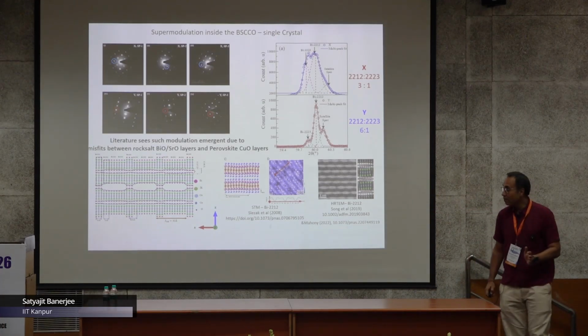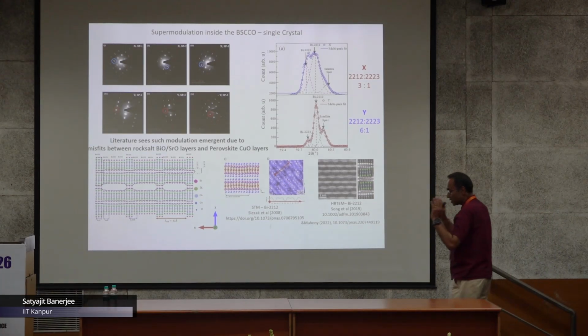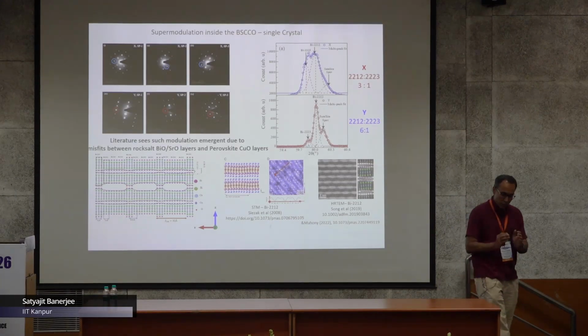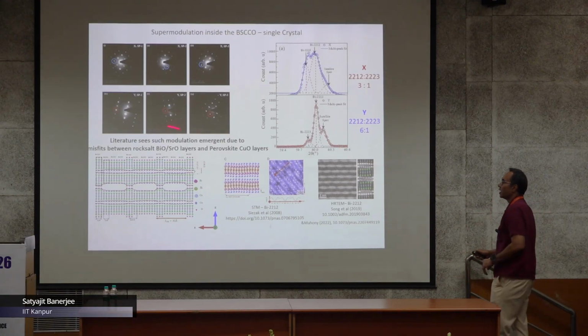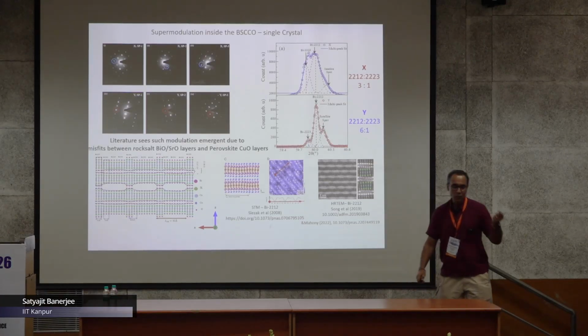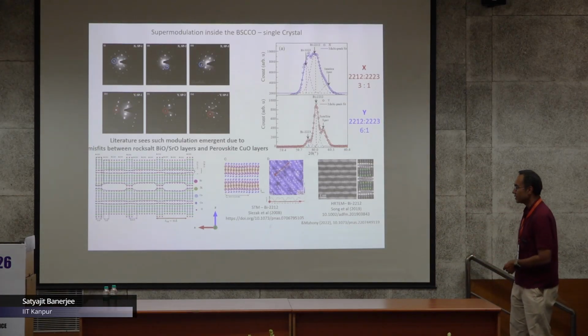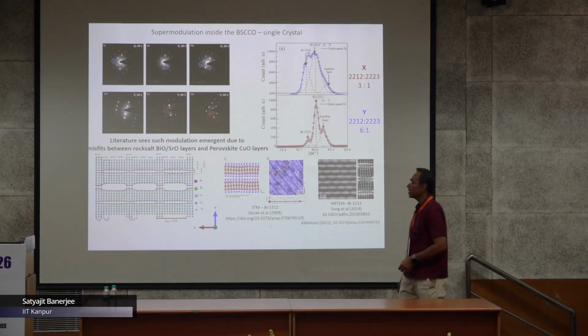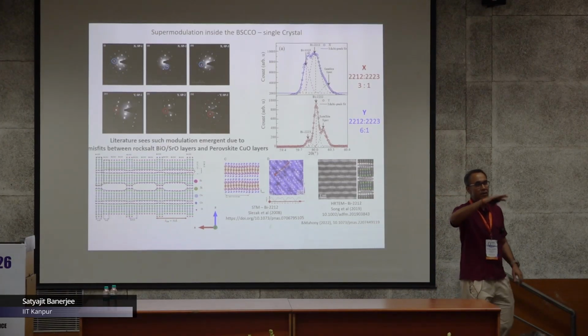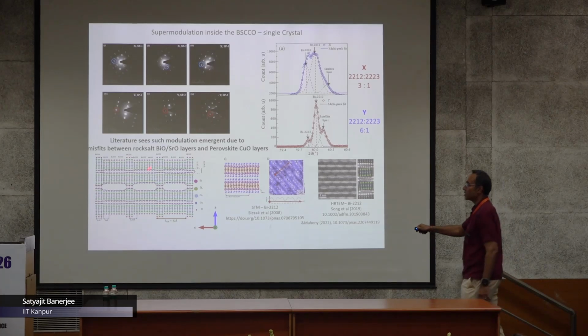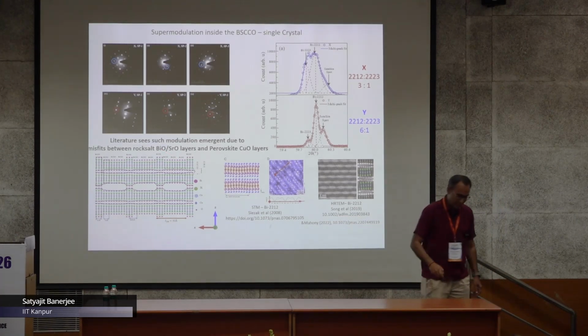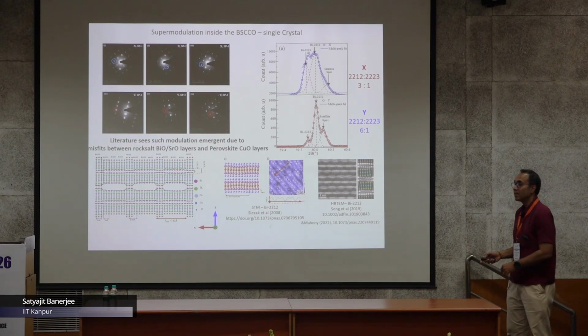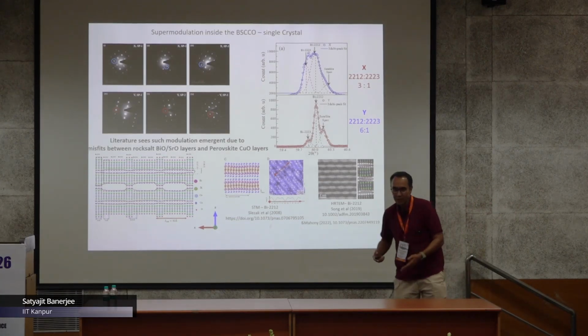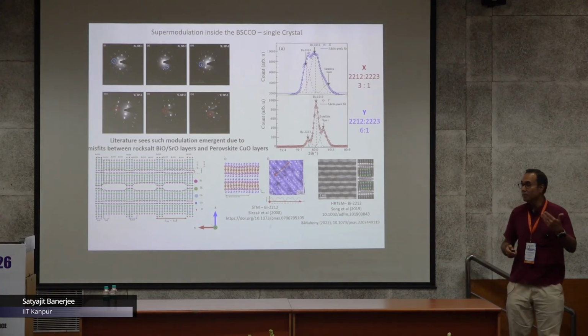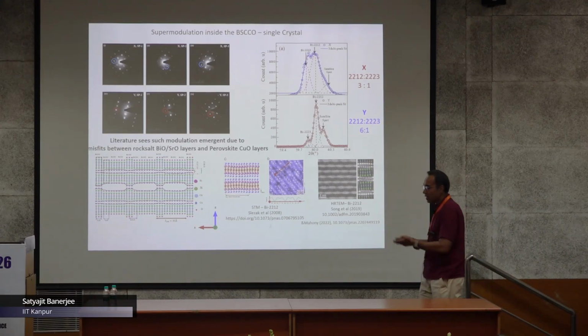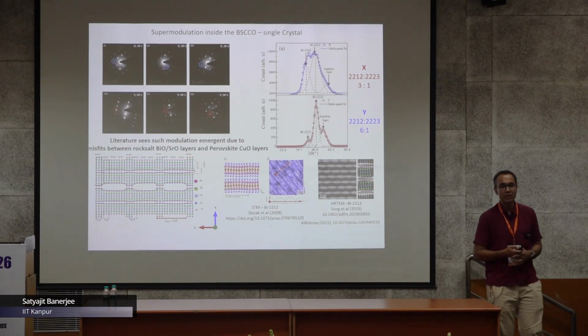So whatever the mechanism—it could be intrinsic strain, which is definitely present, but also this often-missed feature that a little bit of 2212 and 2223 can both be present inside the system—the most important aspect is that intrinsically inside the crystal there is a modulation in the crystalline order. Now, does it lead to anything more than that, or is it just a modulation inside the crystal? Does it couple to the vortex state in some way? These are superconductors with transition temperatures of around 100 Kelvin or so.